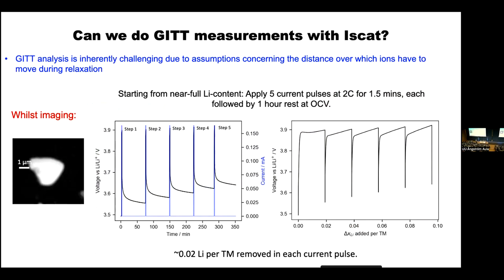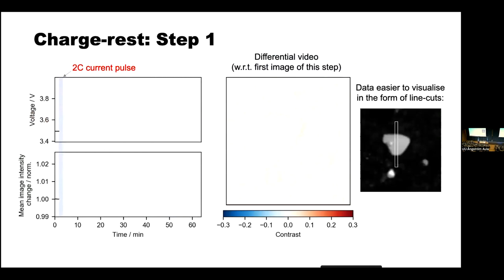This is an experiment where we're giving five constant current pulses at rates of about 2C to extract the first 0.1 lithium. Let's just look at that. This is the first current pulse, and you can see you pulled a little bit of lithium out from the edges of the particle, but that particle is taking a long time to equilibrate. Then you put the next current in, and it's going to be slightly better, but it's still going to take a long time.